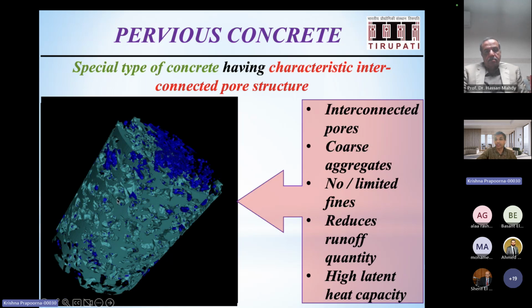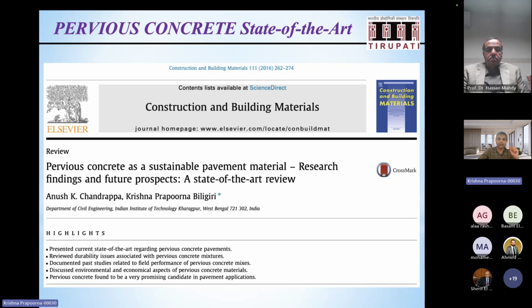So if you have a composite structure, so you prepare this in 3 or 4 lifts, you can start removing the top layer and then replace it with another layer over time. So we have seen that these materials get clogged only once in 3 to 5 years, not less than that. So if you can prepare a top section with pervious concrete, and then also below layers, also pervious concrete, you can start using double or multiple layers of pervious concrete. Only the top layer will be removed every 3 or 4 years as a maintenance strategy, right? So that is another way of dealing with clogging there.